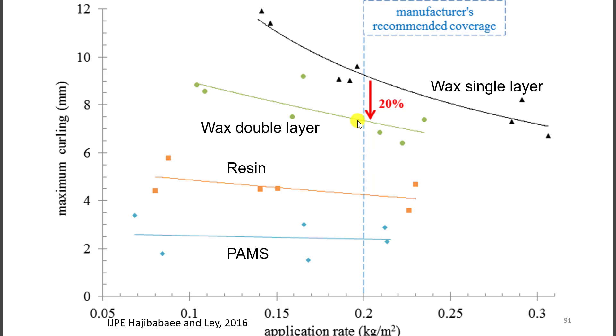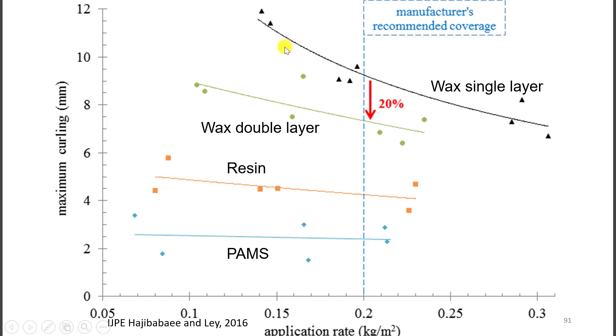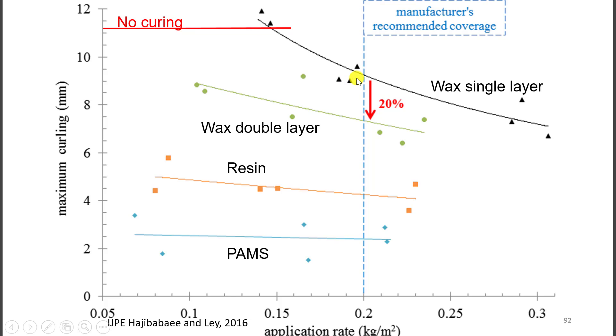This doesn't mean twice as much. This means half as much the first, then half as much the second, and that sums together to get the same amount as if you did it in a single layer. We compare that to resin. Then again, we compare that to PAMS. Look at this. We can use way less PAMS and it actually performs really well, but that's not true for our single layer. Look at that. Here's our no curing line. If we don't get enough curing compound on, if we're not at the manufacturer recommended dosage for curing compound, it's the same as not curing.